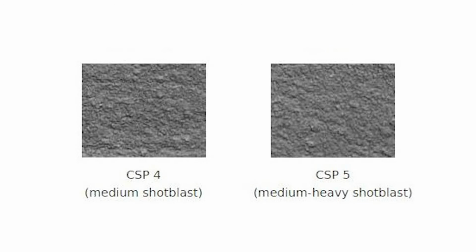What's happening with a shot blaster to be able to produce the range of profiles, 3, 4, 5, let's say, is going to be the time that the machine is allowed to do its work over a given space, or how fast it traverses the surface of the concrete, like a sandblaster or a power washer. If you leave the nozzle in one spot, it's going to dig deeper into the substrate that it's being directed at. Shot blasters the same way.